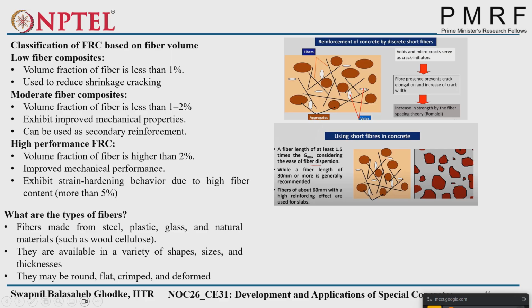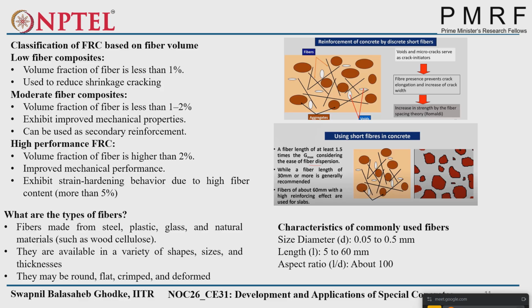Fibers of about 60 mm with a high reinforcing effect are used for slabs. Fiber reinforced slabs are also cast. In that case, 60 mm, that is longer fibers, will generally be used. So what are the common characteristics of the fibers? Diameter 0.05 to 0.5 mm. Length will be 5 to 60 mm. Aspect ratio is one of the major important parameters, called the length to diameter ratio, and that will be about 100.